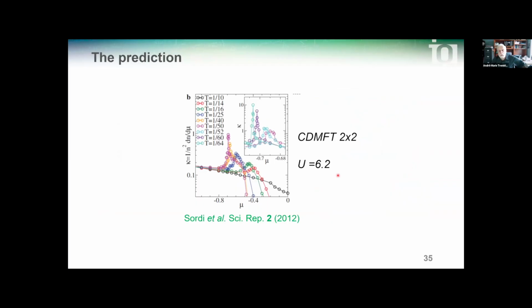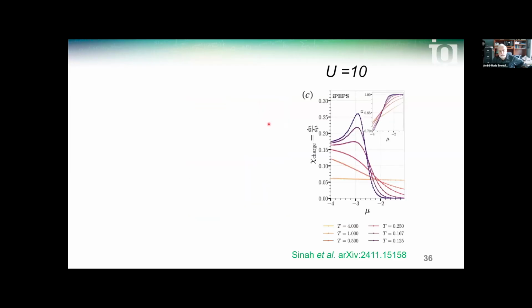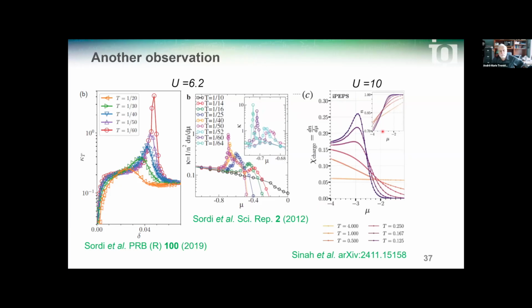This is then the prediction for the compressibility as a function of chemical potential for various temperatures from CDMFT. The divergence at the critical point here, I mean, it's a log plot. It's clear that it's going to become pretty big. This plot of the compressibility as a function of chemical potential obtained this time from IPEPS at U equals 10 confirms this compressibility maximum. Obviously, the different values of U and so on.